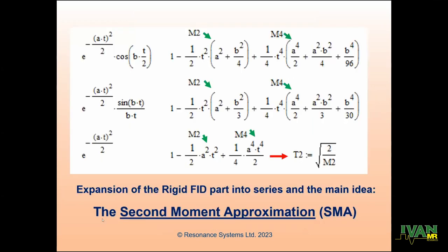And if we look at the classical functions that are describing this oscillation in FID, you can notice that when you do the Taylor series expansion of them, they all have only even contributions in the expansion. And you know that the contribution of the second power is the second moment, and the fourth power the fourth moment. But in terms of the second moment, the beginning of all these curves can be somehow described by just a squared parabolic function.